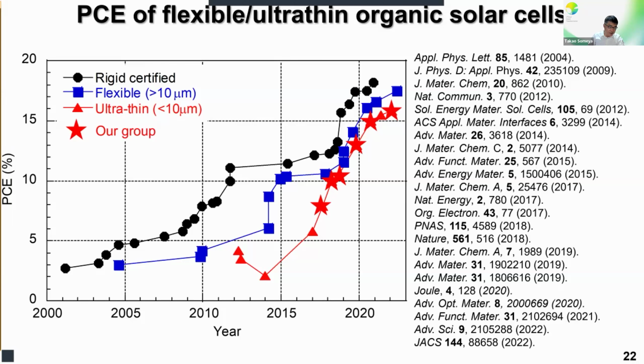So this is the efficiency as a function of the year. The dark black dots are OPV manufactured on rigid substrates, and the blue squares are the efficiency of OPV manufactured on plastic foil with a thickness larger than 10 micron. And the red data is the ultra-thin film with a substrate thickness less than 10 micron. You may see the reduction in substrate thickness makes it difficult to achieve higher efficiency. Why? There exist two reasons.